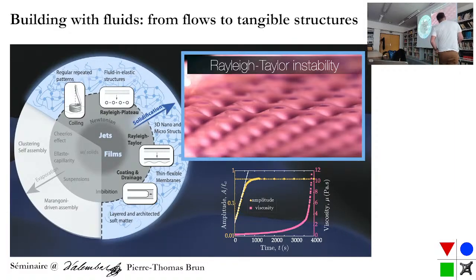In this case, so this is the viscosity of the polymer as a function of time. So basically this is more like a doomsday equation, right? So you have mu, which is mu zero, the initial viscosity, divided by something that goes to zero violently, at about 3,000 seconds. But for the time of the experiment, this is more or less constant viscosity.